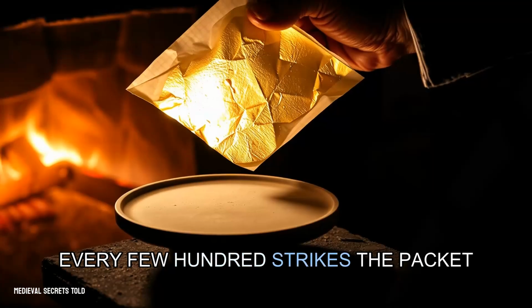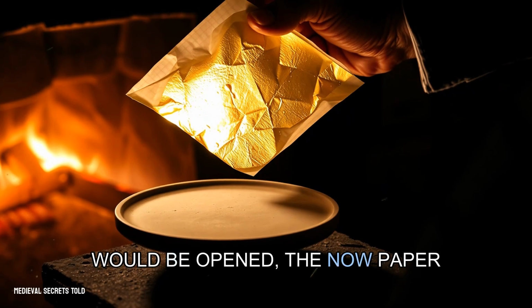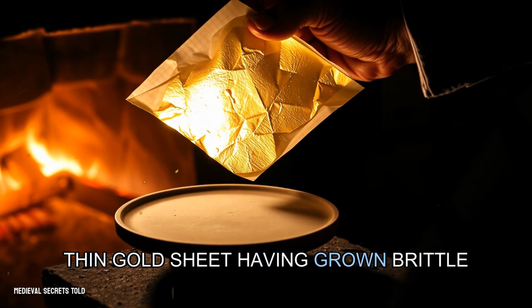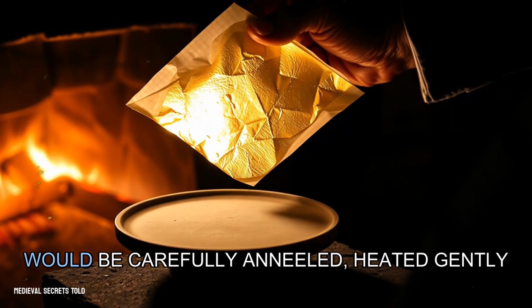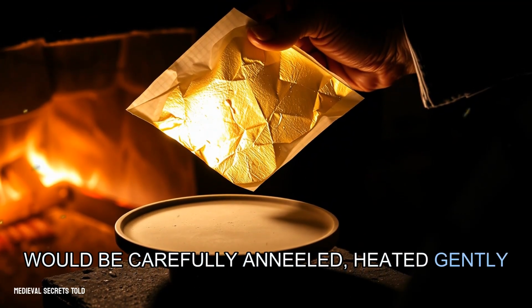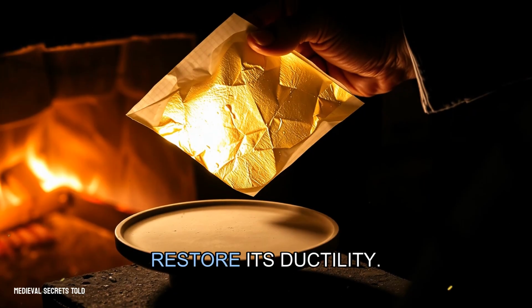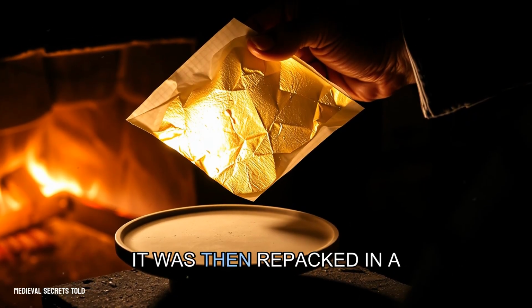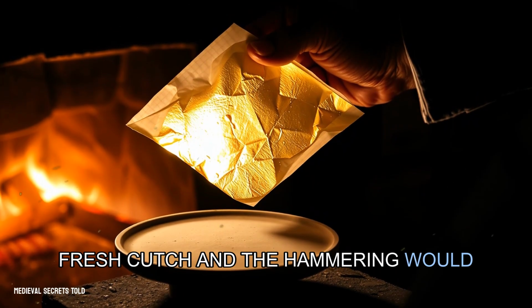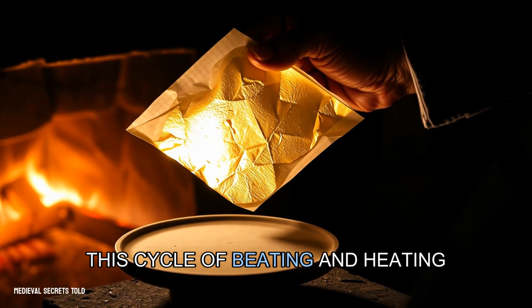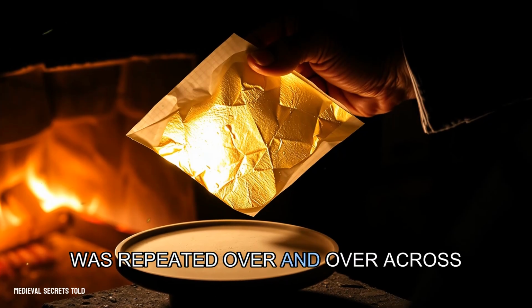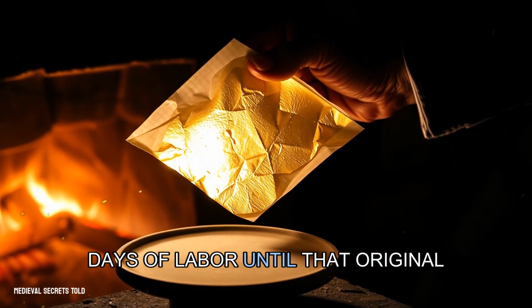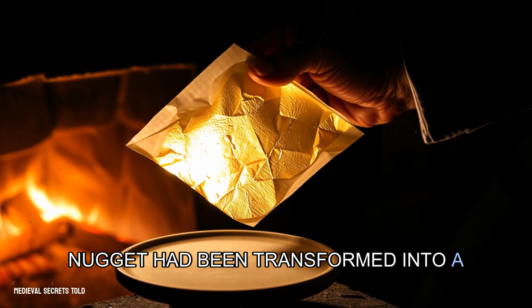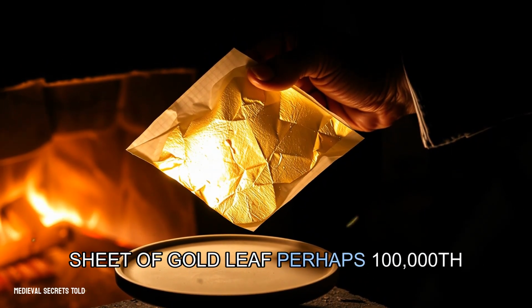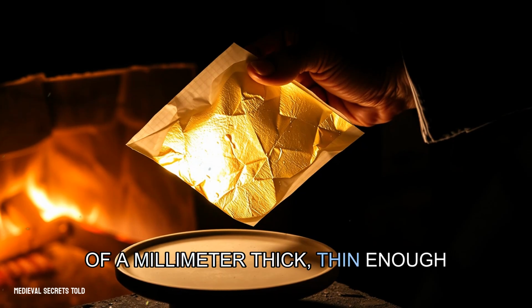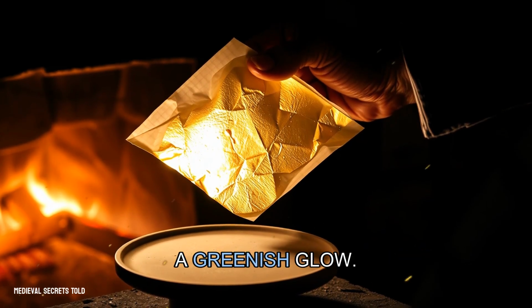Every few hundred strikes the packet would be opened. The now paper-thin gold sheet, having grown brittle from the constant hammering, would be carefully annealed, heated gently to relax its internal structure and restore its ductility. It was then repacked in a fresh cutch and the hammering would resume. This cycle of beating and heating was repeated over and over across days of labor until that original nugget had been transformed into a sheet of gold leaf perhaps 100,000th of a millimeter thick, thin enough that light passes through it with a greenish glow.